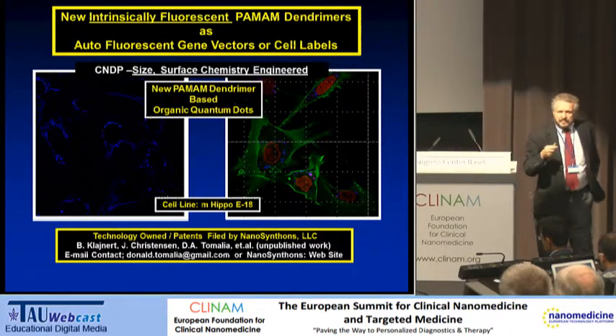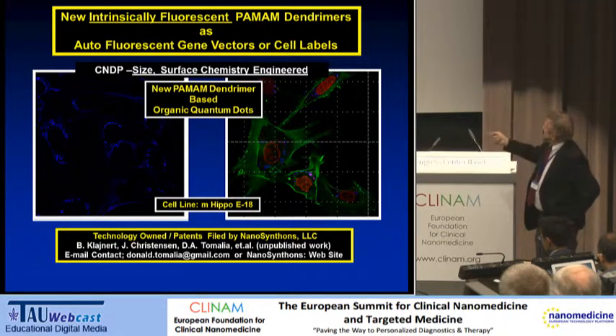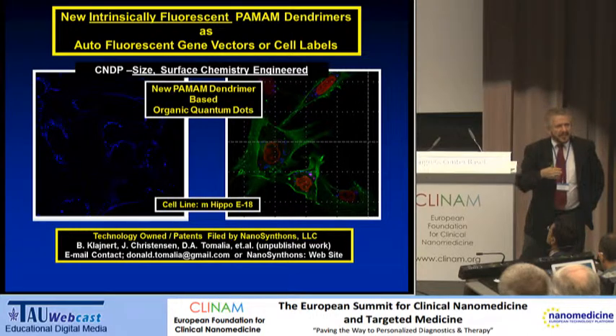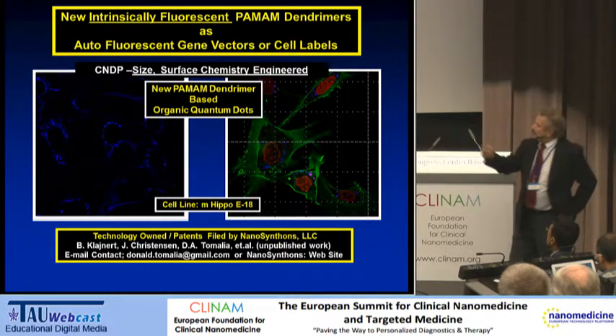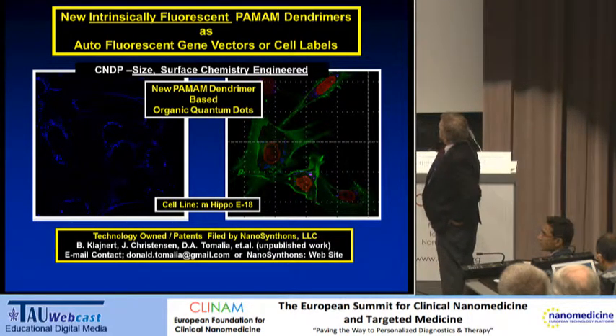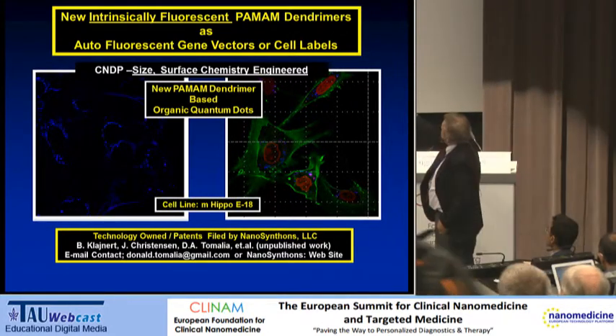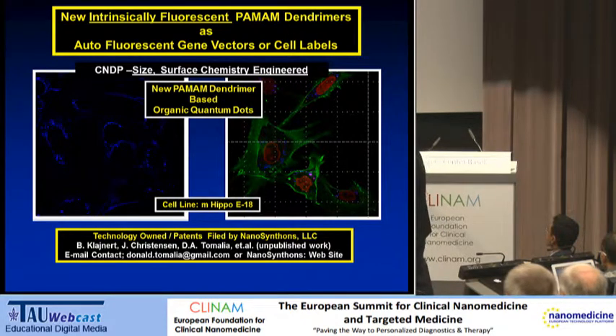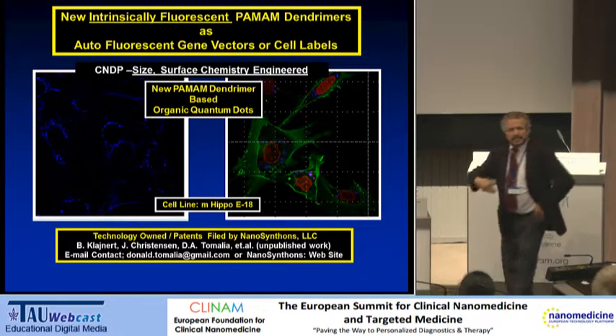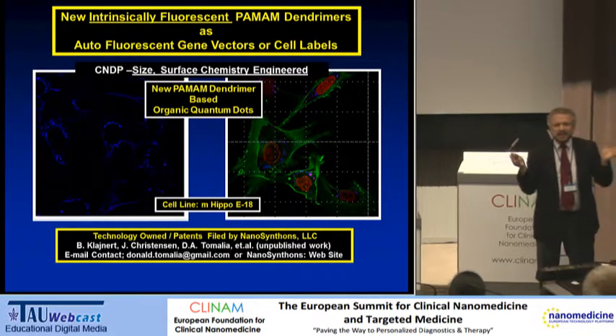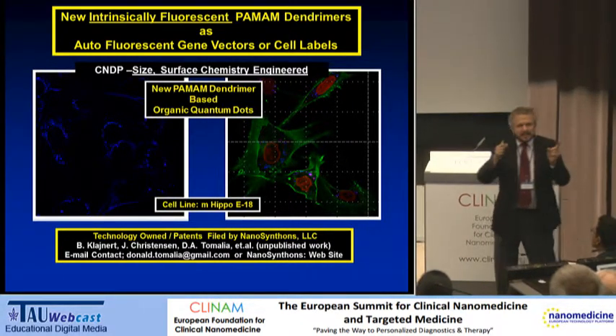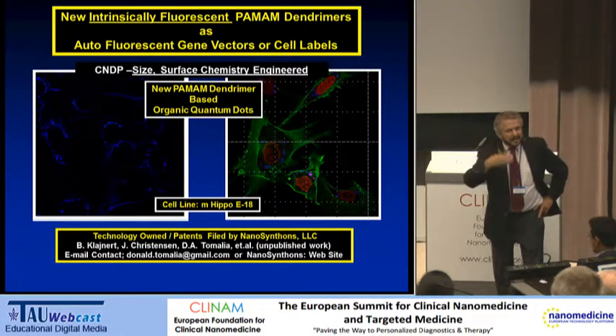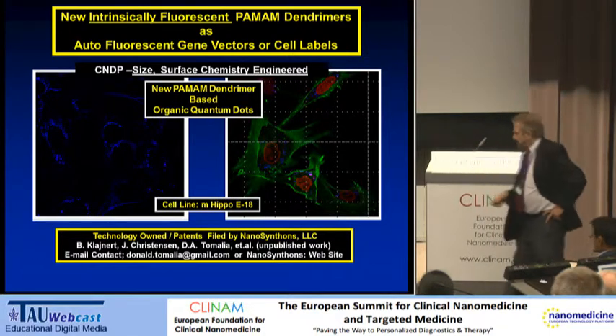One very interesting surprise: working with Professor Jorn Christensen at the University of Copenhagen, by simply engineering the CNDPs of size and surface chemistry, we have recently discovered what is equivalent to the first organic quantum dot based on dendrimers. We have developed sufficient intrinsic fluorescence in the PAMAM-dendrimer series through this engineering that we have autofluorescence suitable for gene vectors or cell labeling. The blue dots visible here are the dendrimers fluorescing intrinsically.